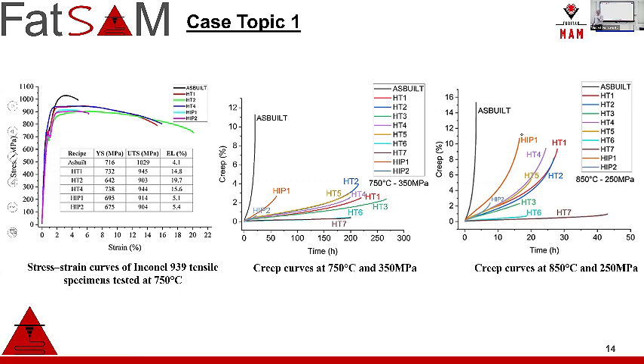As I said before, this is mostly related to the rafting mechanism, the dynamic precipitation of gamma primes, because initially they can be cubic and they precipitate during the service condition as a cubic secondary gamma prime, or in the case of 718, which I will explain later, gamma double prime. So in any case, whether you look at dislocation motion, grain boundary sliding, or grain boundary migration, the mechanism defines the critical resolved shear stress, which requires less plastic deformation during the second stage of the creep mechanism.